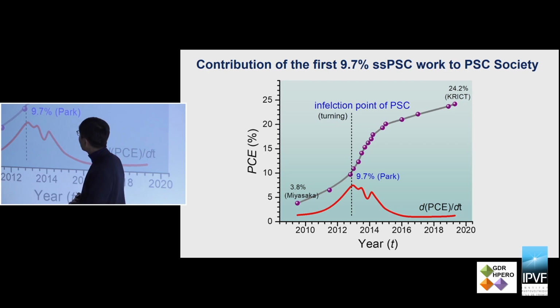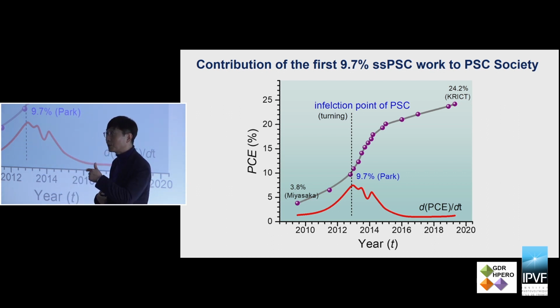Because I'm curious about the contribution of our work, the solid state perovskite solar cell, I took the power conversion efficiency as a function of time and took the first derivative, because with the first derivative you can see the inflection point, which is the turning point. And we found that our work is actually the turning point of perovskite photovoltaics. That means our work contributed significantly.